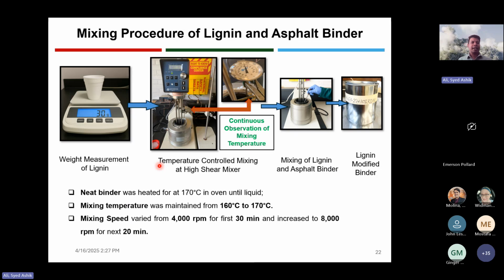Okay, so this slide shows us the mixing procedure that Louisiana Tech developed and used for this product. At the beginning, obviously, we have to have a liquid asphalt binder. So we heated up the asphalt binder at 170 degrees Celsius. Then we measured the amount of lignin that we need for this purpose. And then we started adding that lignin into the asphalt binder and mixed it using a shear mixer.